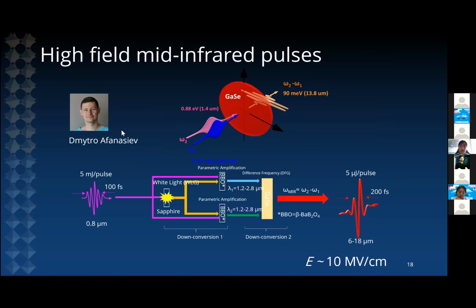And here I'm highlighting the work of Dmytro Afanasiev, who has been working on developing a high-field mid-infrared source. So we start from the output of a titanium sapphire laser that has about 5 millijoule per pulse. And we use parametric amplification and difference frequency generation to generate pulses in the mid-IR that we can tune in resonance with an infrared active phonon mode in the material. So we start from a laser pulse that carries 5 millijoule per pulse, and we end up with 5 microjoule per pulse at the end.